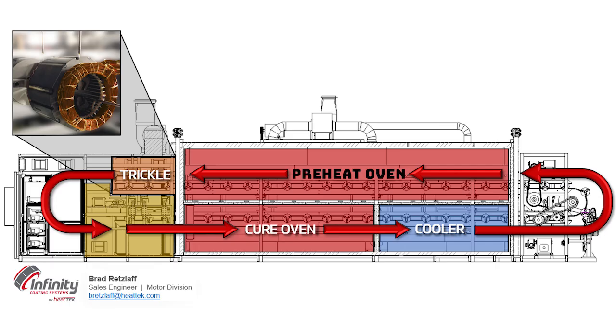Here's what a typical trickle application process looks like. On the right, you see where the part is loaded, typically by hand or robot. Next, the stator will travel into the preheat zone while rotating at 10 to 20 RPMs. The stator is typically preheated to between 80 and 100 degrees C. Time needed to get the part to temperature depends on the mass of the part. It typically takes 30 to 45 minutes to reach the desired temperature in a convection oven. Other heat sources, such as induction or resistance, can be used to shorten the time to temperature.